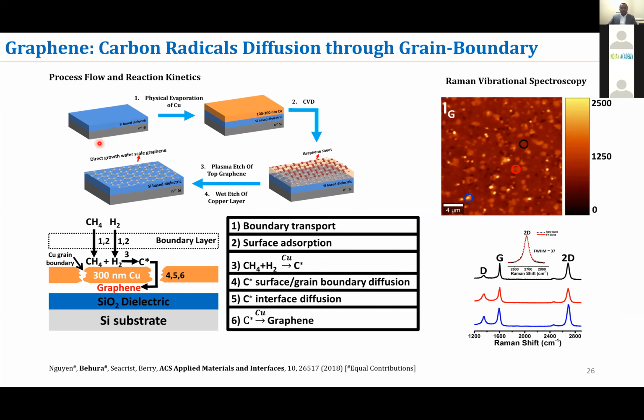So what we have done, we have a silicon substrate and we used a layer of copper. However, the copper is highly polycrystalline. And so that means it has a lot of grain boundaries. Not only the grain boundaries you can see from the top, but also some of the grain boundaries that are connecting from top to bottom. And then we did exactly the same process as I showed earlier, used methane gas to decompose into carbon and hydrogen, and then carbon radicals now diffuse into these grain boundaries and started nucleating on the silicon oxide substrate directly. Now you are forming a layer of graphene between copper and silicon dioxide.